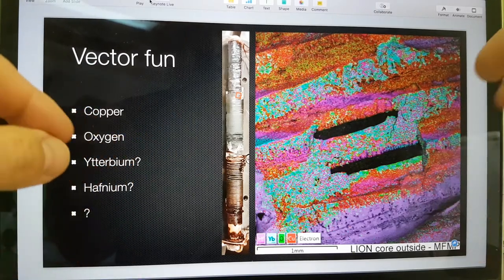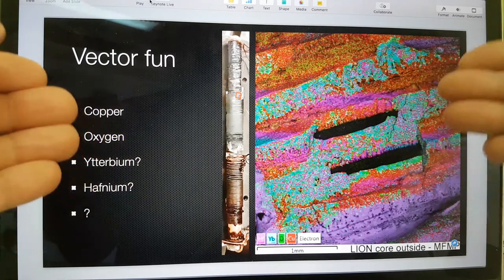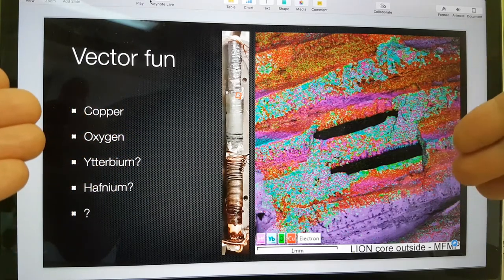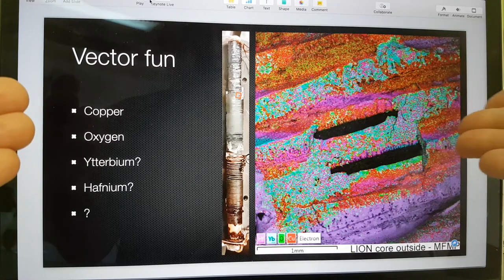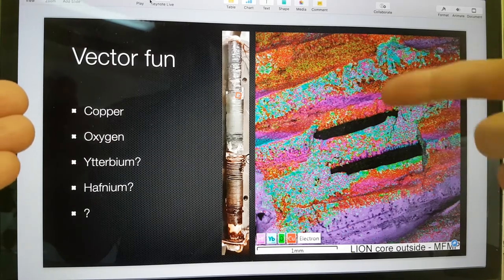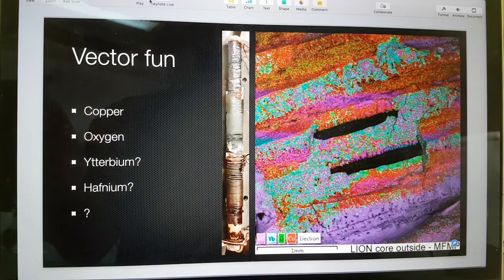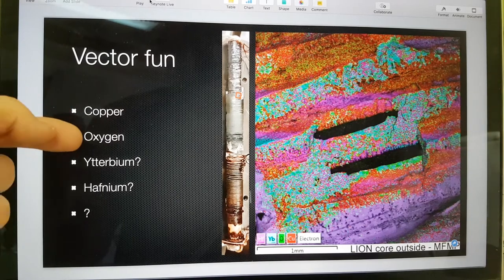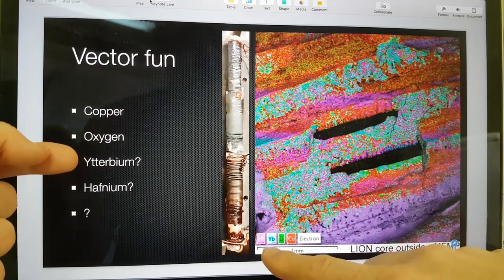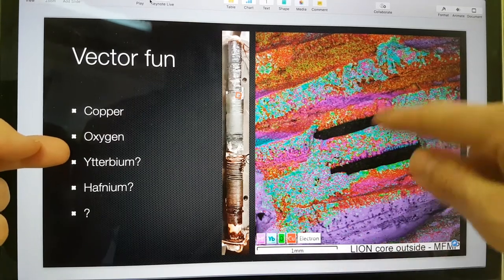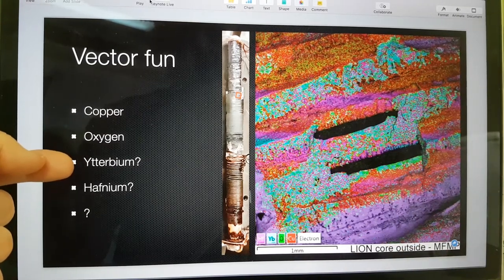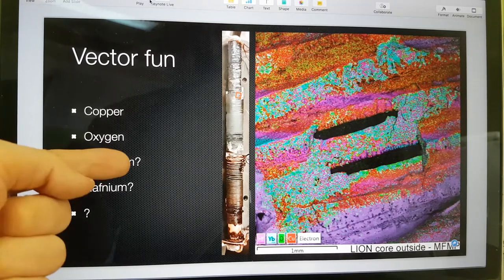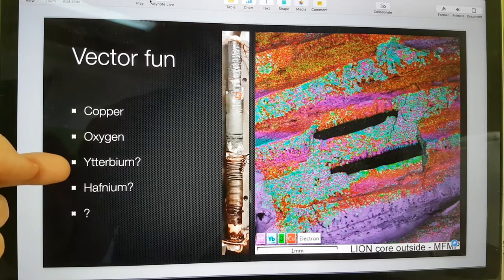Sometimes there are impurities in there, which the EDS determines. But it only comes after LENR reaction, like is seemingly going on in the Lion reactors, that we really start having some challenges in finding out what the elements are. One thing that was quite interesting is it seemed to have this ytterbium here. So this cyan color here, there seems to be some ytterbium.